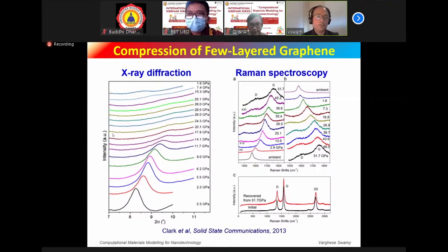I will quickly go over to some experiments on multi-layer graphene. This is a published paper. What is shown here is the compression of multi-layer graphene, an X-ray diffraction study up to very high pressures. You can see that this is the diffraction peak of graphene. At some point, around 12 GPa, this peak disappears and the material becomes disordered. This result is supported by Raman spectroscopic data also.